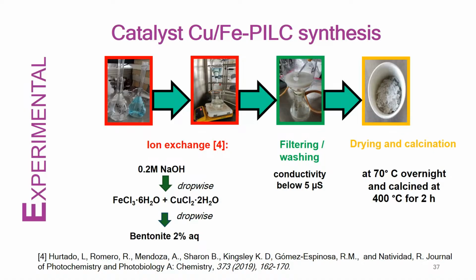Thank you very much for your presentation. It was very interesting. My question is, how can you solve the recombination? Because you mentioned it is a problem. Yes, the charge recombination or the oxidation of the formic acid? No, the charge recombination, the electron. When you dope a material with a metal like copper, the copper can work as a trap for the electrons, and that is the reason for doping the titanium dioxide with metals. But another strategy is also increasing the oxygen vacancies, because those oxygen vacancies work as electron traps also.